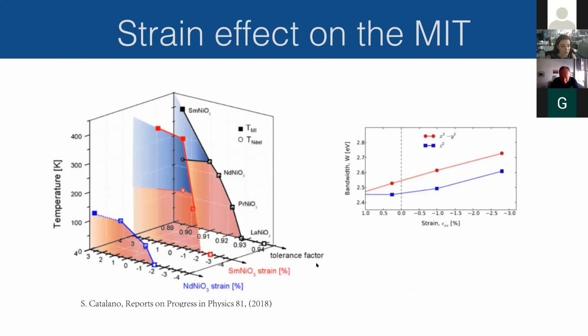So one of the things that comes out, of course, when you make a heterostructure, which we already touched on a bit earlier, is that you have a renormalization of the bulk properties. So that means you're not really inducing new physics, you're getting the same physics, it's just happening in slightly different conditions. So here, this picture is showing the bulk phase diagram, or part of the bulk phase diagram, expressed as a function of tolerance factor, compared to two thin film systems. So these are thin films of samarium nickelate, and these are thin films of neodymium nickelate. And here you see that as a function of strain, which you choose just by changing the substrate that you grow on, you get something that looks quite a lot like the bulk phase diagram. It's just shifted in temperature.